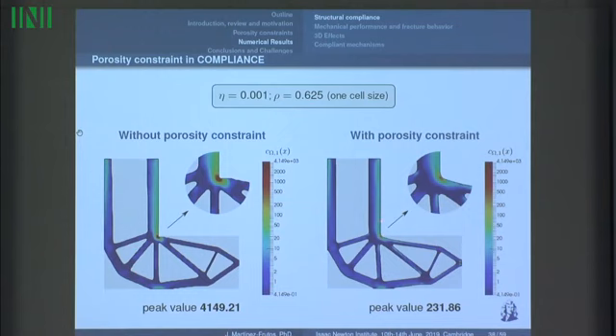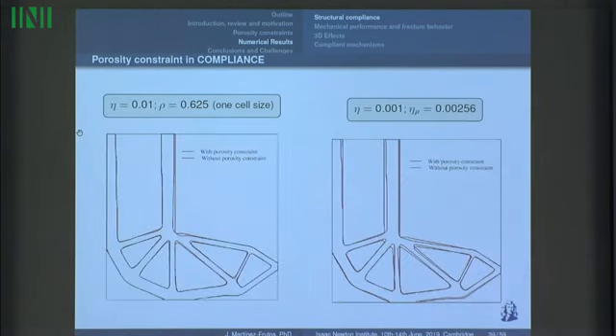This modification of the shape can be shown in detail if we overlap the design without the porosity constraint and the design with the porosity constraint. We see that we have a smoothing of this sharp region, and also these regions that connect more than 3 bars are larger and more rounded, whereas in the previous one the modification of the shape is more local in this corner.